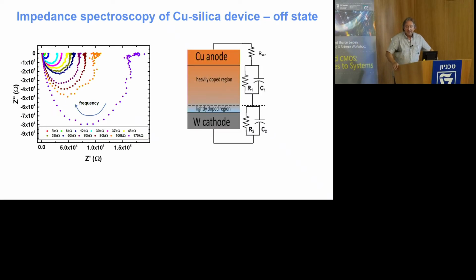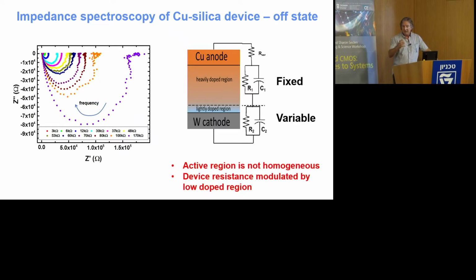And in this case, you look at the Cole-Cole plots, and you see that the structure of these devices is actually not homogeneous. Typically, we've got in essence something that has a low resistance on top of a region with a higher resistance, and you end up switching the higher resistance, and you can see this as a kind of dual RC type of structure here. So you're really in these devices, and we can see this by impedance spectroscopy, modulating that high resistance region, which is actually kind of cool.